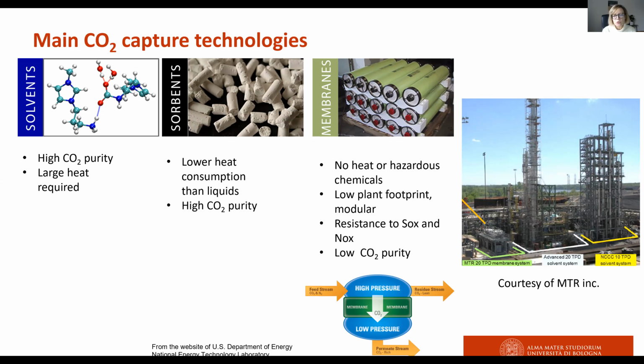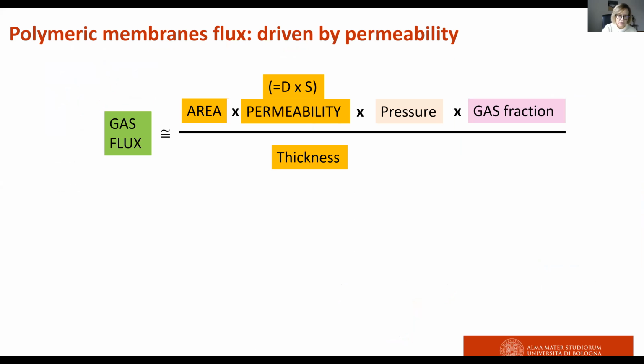Most CO2 separation membranes work in this way. They have a membrane which preferentially permeates CO2. You feed your feed stream, which can contain CO2 and nitrogen, or CO2 and methane, or CO2 and hydrogen, depending on the capture scheme that you are using. You compress this stream, and this is the main cost associated to membrane operations, the compression cost. And what you get is a low pressure permeate stream, which is enriched in CO2, and a CO2 depleted residual stream, which is still at high pressure. This occurs in the majority of the cases.